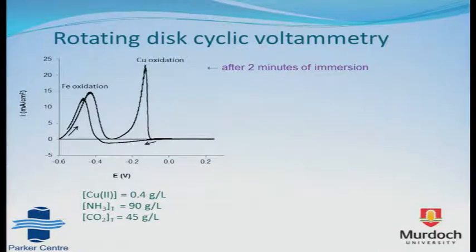The fact that iron passivates in this transition is confirmed by voltammetric measurements. We don't need to go into too much detail here, but if by varying the potential in a scan prior to the open circuit potential transition, you see that there is oxidation of iron, meaning that iron is still active at this stage, and then it's followed by oxidation of the copper as you increase the potential. And once all the copper's dissolved off the iron, as you increase the potential further, there's no longer any current. And then it's scanned back in the reverse direction and you don't get any current. Then you start to get a reductive current and again, dissolution of iron.